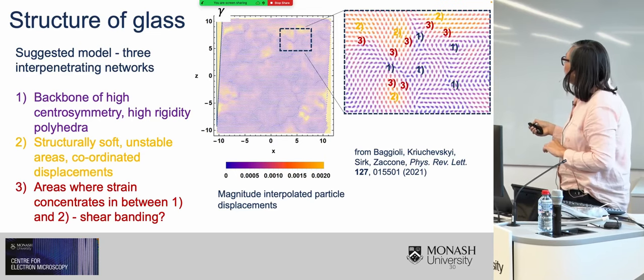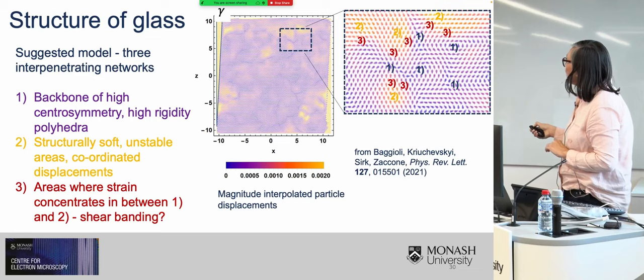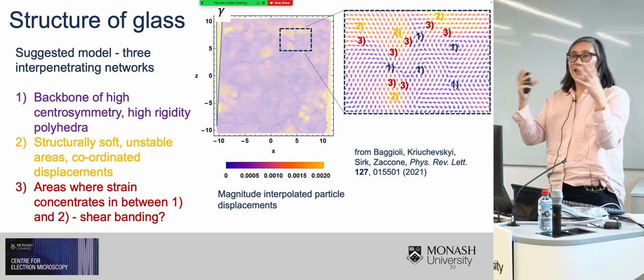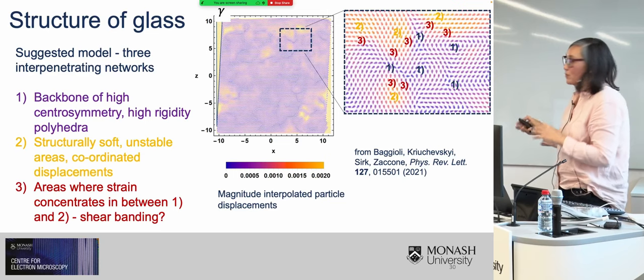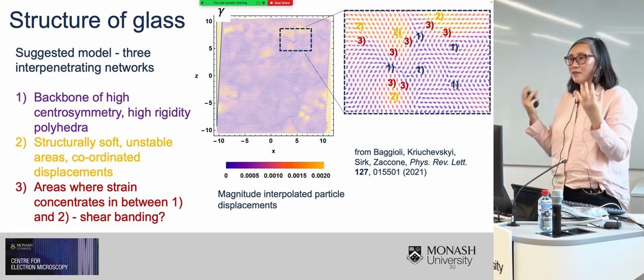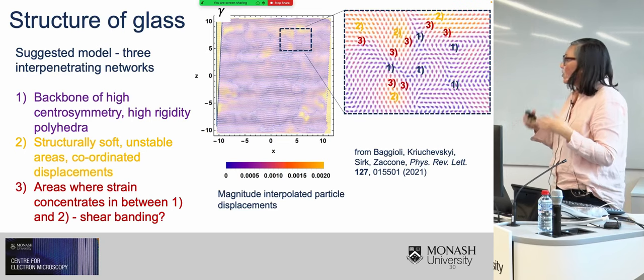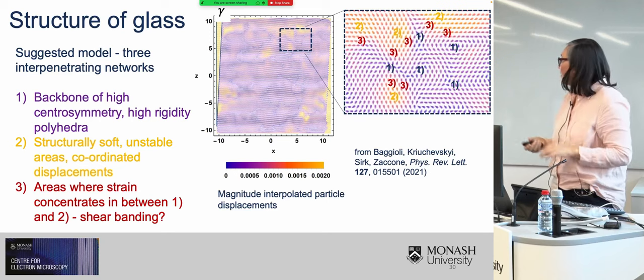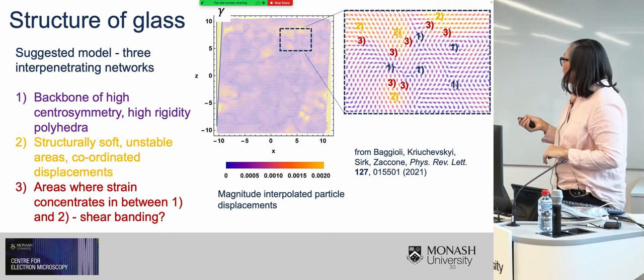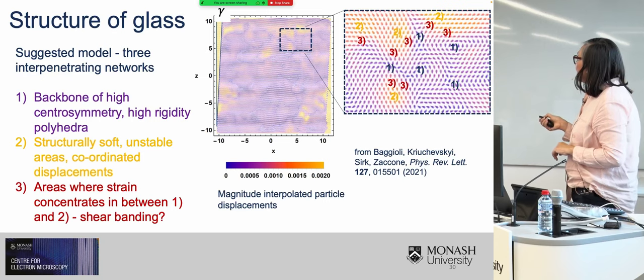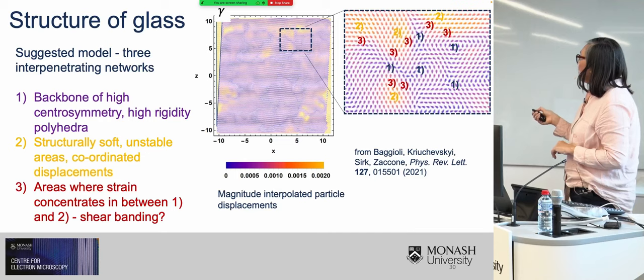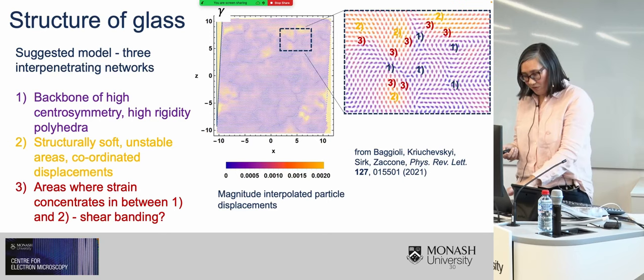So for example, here, where you have your net flow of particles away, but this area still has local dilation. And here you have some local contraction. And so this model actually explains the correlations and anti-correlations that I see in my measured maps. Now, looking at these interpolated displacement fields, you can see that there's actually something curious about these points of low displacement. And often, if you look at the displacement field around them, you can detect some kind of net circulation.